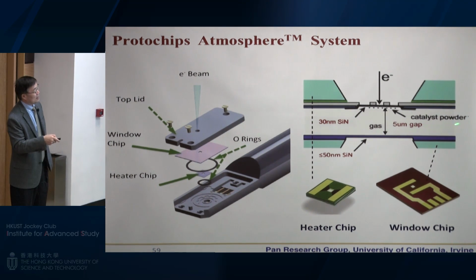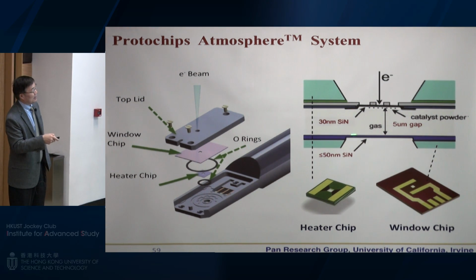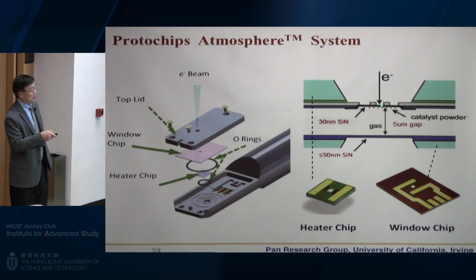So this is just an exaggerated volume of gas. There's a lower silicon nitride membrane, an upper silicon nitride membrane, and then there's also the E-chip. You can heat the sample to 1,000 degrees C. And then you can see how this gas interacts with a small particle of catalyst, which is put on the top part of the membrane.